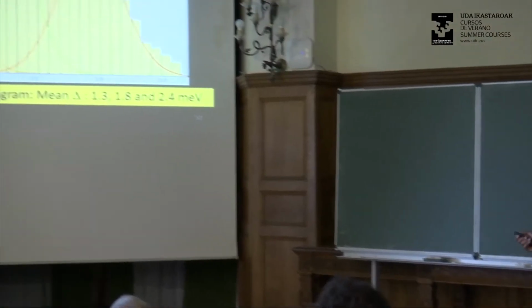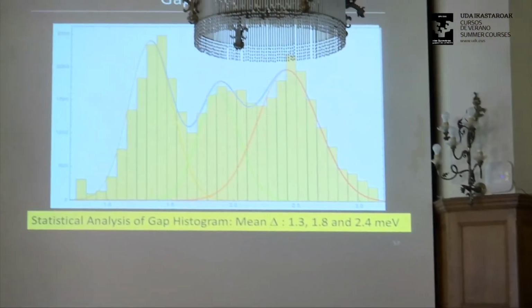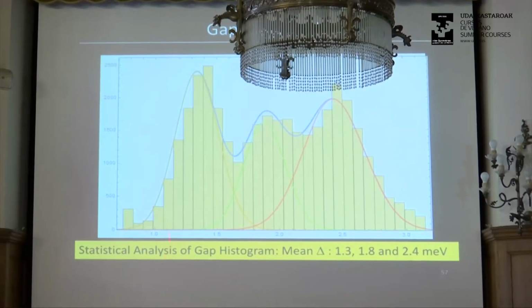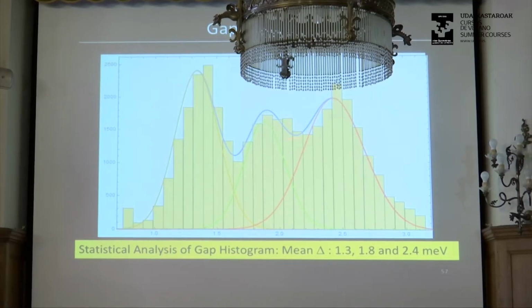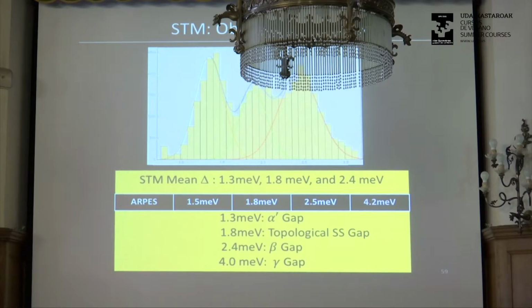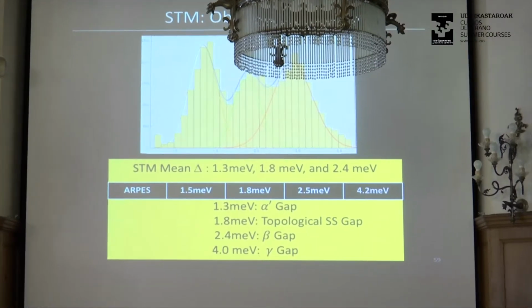And now you can go to all the 3 gap regions, and this is what the gap histogram looks like. Like I said, this is hundreds of thousands of spectra. From here, you can just fit 3 Gaussians to this and extract the mean gap values. These are the numbers we get. And the fact that we have 3 gaps, 1.3, 1.8, and 2.4, already tells you that we probably have a surface state in this system, right?